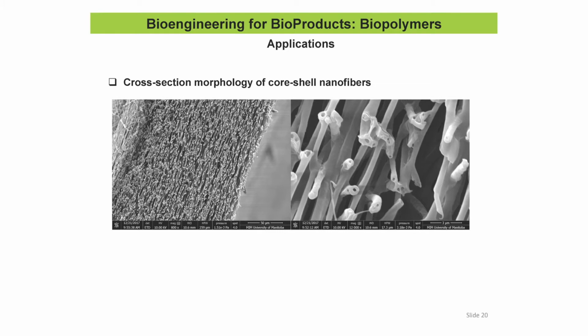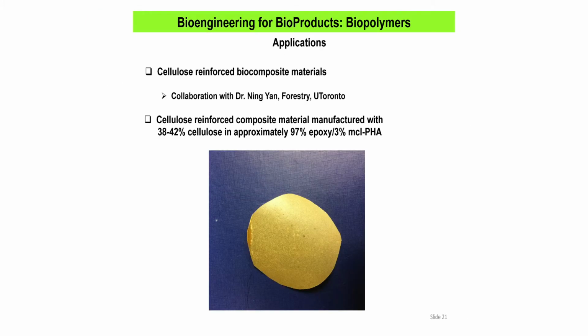Another application is making biocomposite materials, and this is in collaboration with Dr. Ning Yan at the University of Toronto, Department of Forestry. And we gave her some of our PHA polymers that were made from canola oil or from flax oil. The canola oil polymer has about 5% unsaturated side chains, and the polymer made from flax oil, long chain fatty acids, has about 50% unsaturated side chains. And so she mixed it with about 40% cellulose and some epoxy, and we got a material that was like fiberglass.